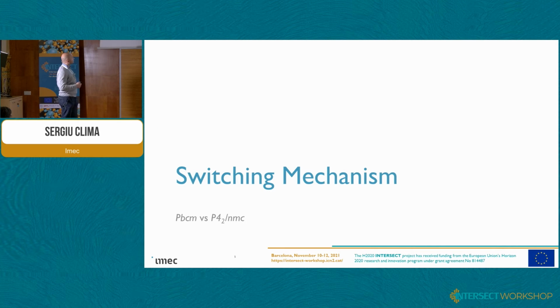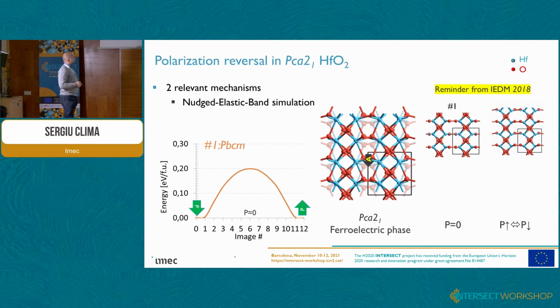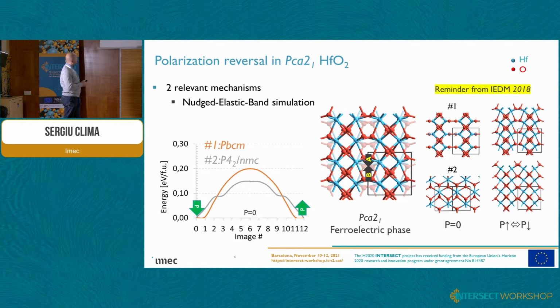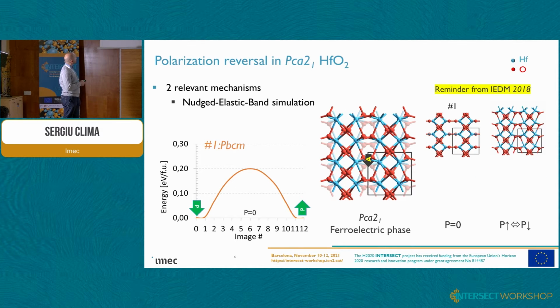Let's focus a bit on the mechanisms themselves. The switching itself can go in two different directions. One direction I call the PBCM mechanism - this is the symmetry of the centrosymmetric position where the oxygen atoms jump across a hafnium plane. Here you see the animation. This switching mechanism shows the characteristics of a perfect Landau switch, in the sense that you can use the Landau equations to describe the switching.